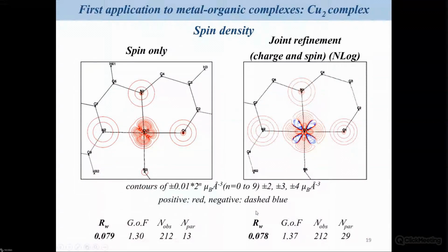It's clearly different if you consider now the spin distribution, because of course, one of the main advantages of the joint refinement is that you can introduce many more parameters in the model, because you don't consider only one experiment, but a lot of information coming from 3 different experiments. And if you look at the numbers given there, you see that the number of parameters in the case of joint refinement that have been applied to the modelization of the spin density is more than twice the one you have for spin-only refinement. And of course, you see that the spin distribution obtained for the copper atom is clearly more precise after joint refinement.